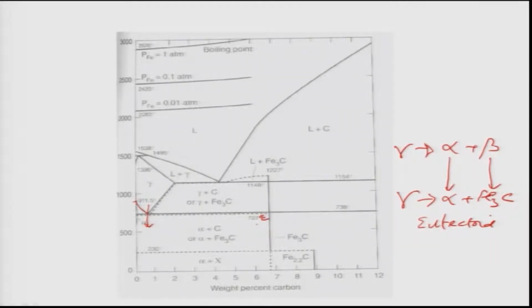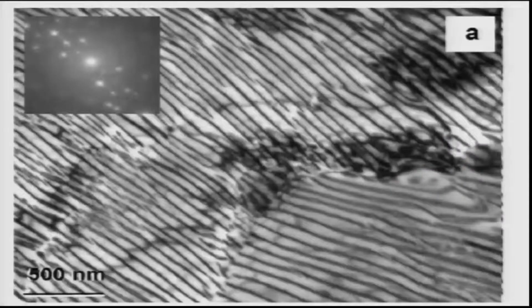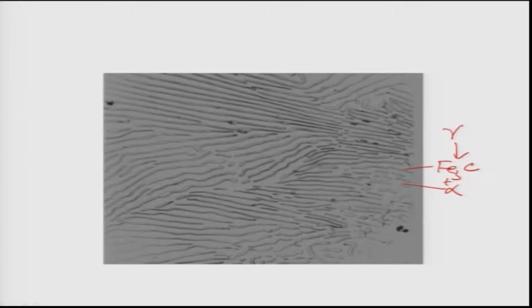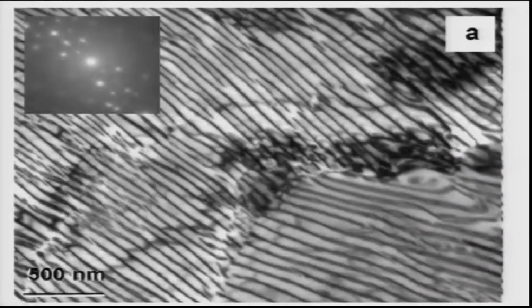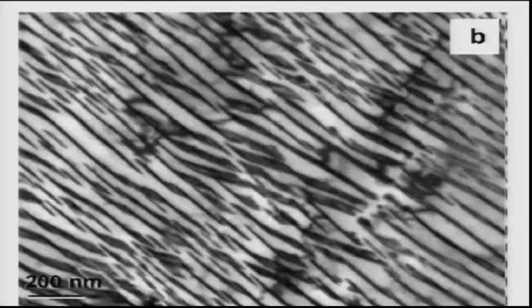Let us now discuss how this transformation actually happens. Obviously any transformation will happen by nucleation and growth, correct. This is the typical microstructure. If you look at it in an electron microscope, it will look like plates. The black thing is Fe3C and the white contrast thing is the alpha phase. It has a nice plate-like microstructure, an alternating arrangement of these phases. Similarly, here you can also see plates. Some of them are broken plates, but this is alpha and this is cementite.